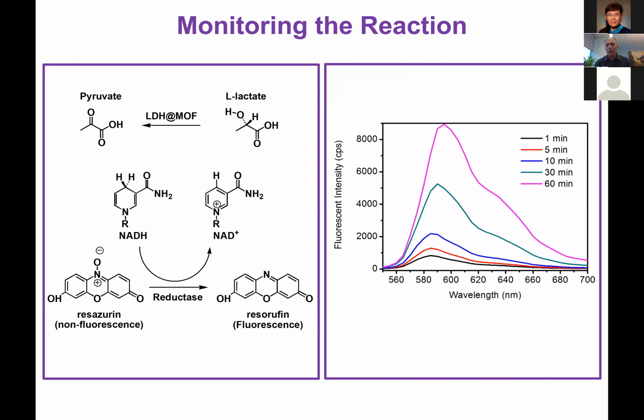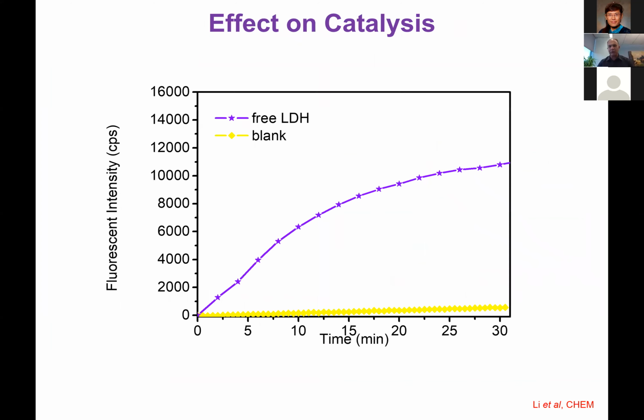So now we do the catalysis. And how are we going to test which MOF works better for that LDH and the coenzyme? We take in lactate to pyruvate, and we could use this non-fluorescent molecule, and when it reacts, it becomes fluorescent and it doesn't go back. That means we could start counting the fluorescence, and that's how we can start distinguishing between the two different MOFs and, you know, the initial rates.